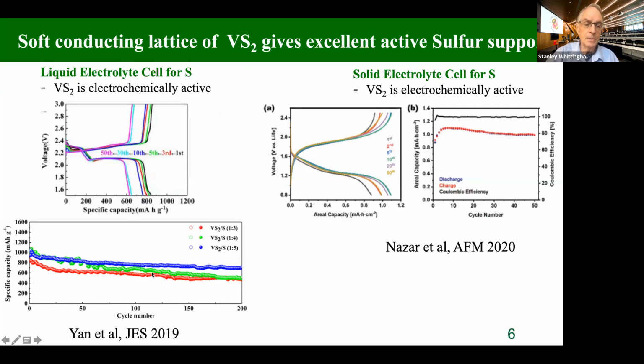And you can see the cycle behavior is very good here. And this is for different ratios of sulfur to the vanadium disulfide. On the right-hand side is more work from Linda's lab. And this was an all solid state cell. And you can see there's obviously more polarization because it's solid state. But again, she got more than 50 cycles out of this. And it helps having this electrochemically active substrate so the vanadium disulfide can intercalate the lithium as well. So people said these layered sulfides are not dead yet. There's still a lot of interest in them for basic research.